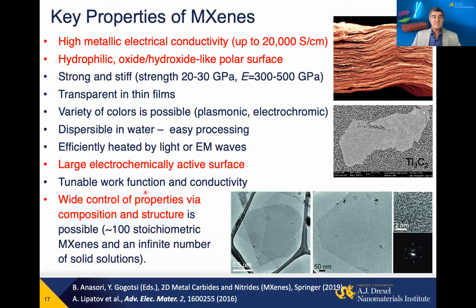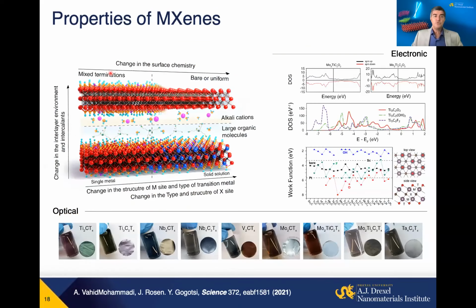And electronic properties are tunable, but what is important? We have really the ability to atomistically design materials. So we can get properties we want. And also there is a big difference, for example, with chalcogenides. We're very limited to the surface being a chalcogen, so we have a smaller number of choices. Here, we have a dozen transition metals, and they are basically oxygen, OH as a bonding source. So we have this very large tunability. We still need to learn how to tune those properties here. How to move from mixed termination to bare uniform terminations here.